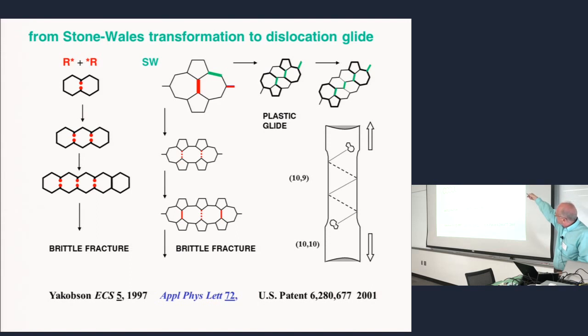If you rotate this bond, you see what will happen? Put it perpendicular, it recovers a hexagon here, and instead creates a pentagon and heptagon here. So this is again an isomerization process, right? You just have another isomer. But at the same time, what happens is quite remarkable, because here you recover the perfect lattice, you have hexagons. And now you split your two objects, which are dislocation cores, which of course you can repeat, and what you see is, not surprisingly, dislocation glide. So now these 5-7s, by just repetition of Stone-Wales transformations, can go further away from each other, and this is your dipole nucleated by the first rotation. Now it splits and can propagate.